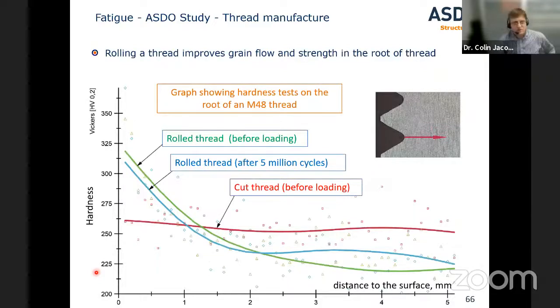We've done a lot of studies on thread manufacture and the improvement in fatigue. And what we found is that if you roll a thread, what happens is in the root here, you get a much stronger material, which aids the fatigue resistance. So we found really this is a rolled thread before we've actually started loading and after rolling. So you can still see we've got high strength, whereas a cut thread has a much lower strength in that root.